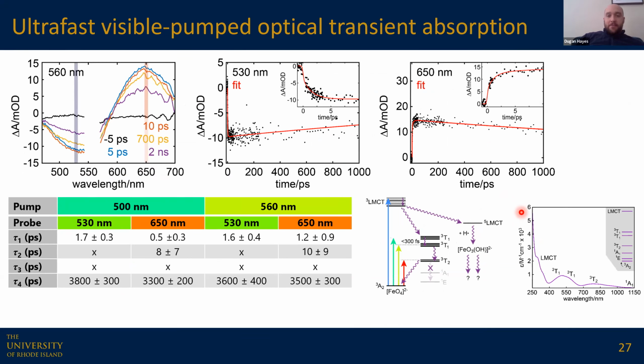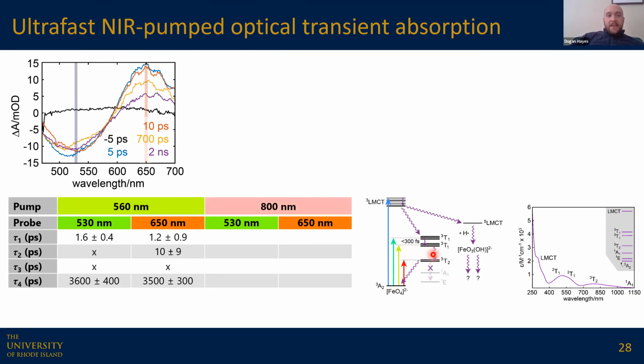And so we can start to put together what we're seeing here on this diagram. And so basically what we're thinking is following UV excitation, we are in this LMCT state, and that can branch between intersystem crossing to the quintet or internal conversion to the metal-centered state. And then this is what we were seeing predominantly at 100 picoseconds. That relaxes by the arrival time of the next X-ray pulse, and so all we observe at that point is this quintet LMCT. And so we can start putting timescales to this, regardless of which visible absorption band we pump into. We don't see any difference in the kinetics. And so this intraband relaxation is very, very fast.